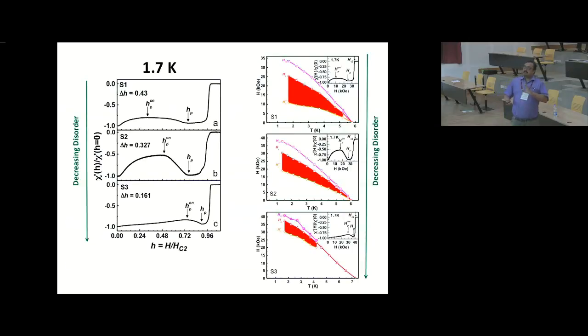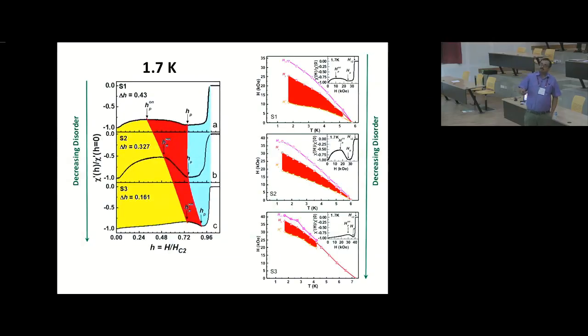But to see whether this could be applicable here, we now measure various crystals which have different degrees of pinning strength. What we observe is this, and these are all done at 1.7 Kelvin. This is the crystal which is most disordered. This is where we start to see these dislocations coming in.